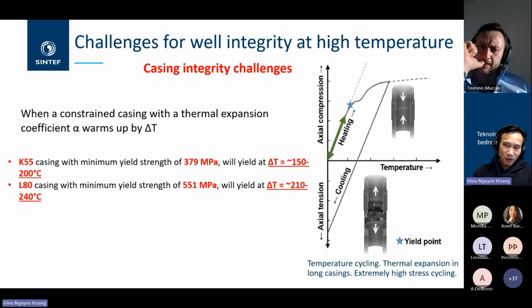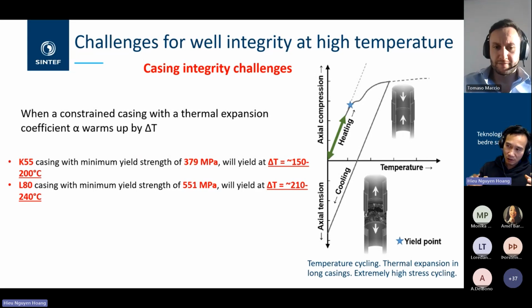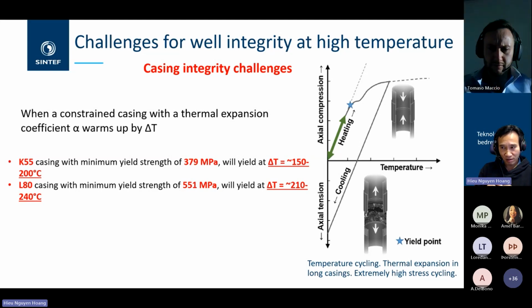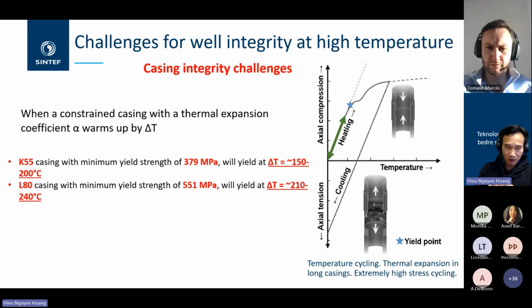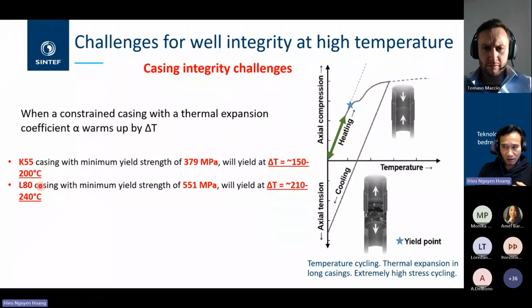Let's have a deeper look into the effect of thermal stress on the casing material here. As you see, this is when we subject this material to a high temperature change. The material, like a casing, experiences a lot of thermal expansion and contraction. And if this thermal deformation is constrained, as in the wells, thermal stress is going to be developed in the casing systems. And the casing material, like the K55 or L80 we use here, has a specific elastic limit, beyond which the casing material will deform plastically. It means that we have a permanent deformation.